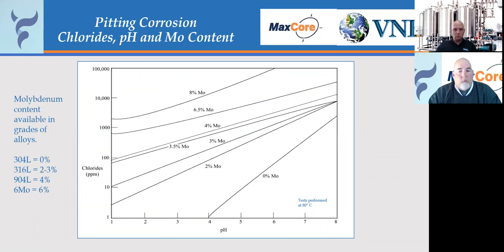If you look at this particular chart, this is a test that was done in a laboratory at 80 degrees C. It shows on the bottom the pH level of a product, and on the left-hand side of the graph is the chlorides in parts per million, and the lines going across the graph indicate the amount of molybdenum content that a material might have. So if you look at a pH of 5, for instance, and you look at a 316L stainless steel with a 2 to 3% molybdenum content, you can see that you can withstand about 500 parts per million of chlorides based upon this graph.